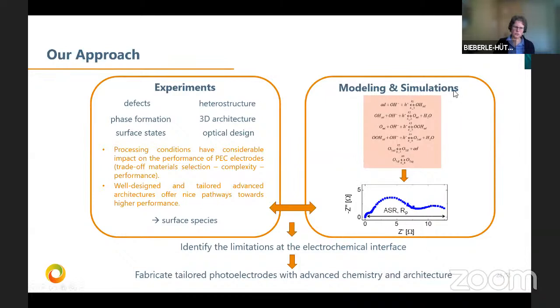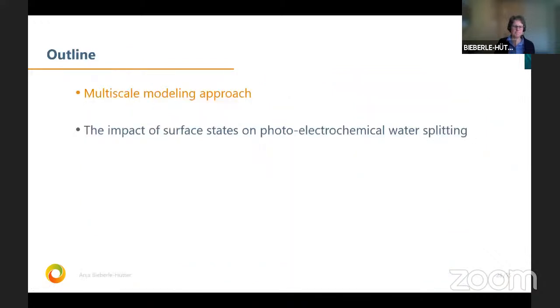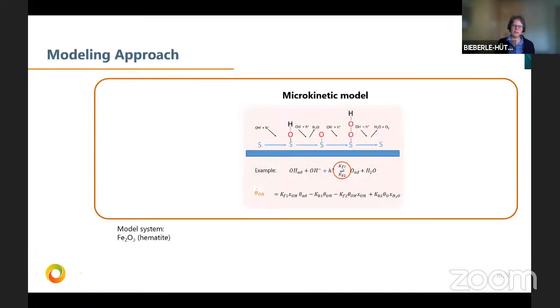I will now go to the modeling and show you how this connects, because these measurements, as I said, are extremely difficult. From the modeling side, we can model these surface species, and this is also where we would like to bring it together. I've split the modeling part in two parts: the multiscale modeling approach itself, and then a case study showing what we can now really do with this. So we do microkinetic modeling. We start with the mechanism from Rossmeisl, the four steps: OH, O, OOH formation, and then O2 desorption.